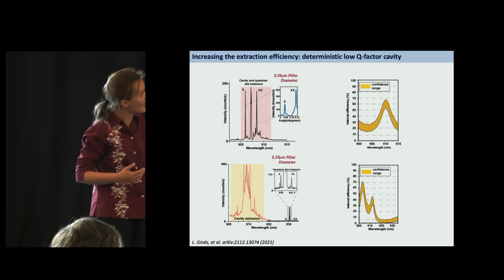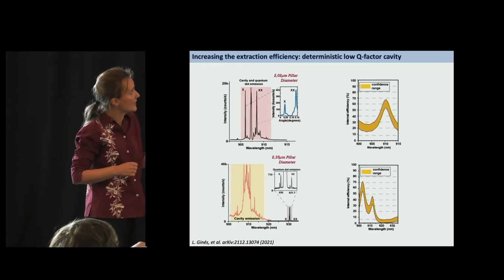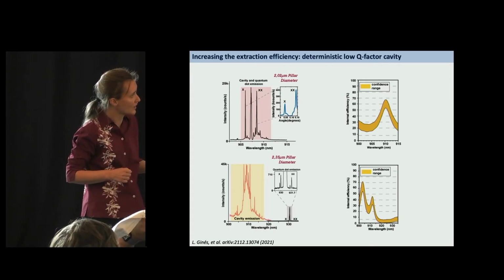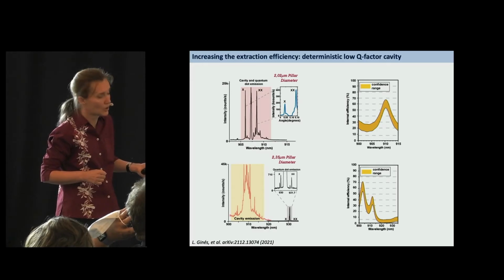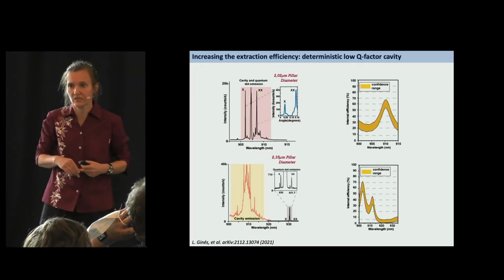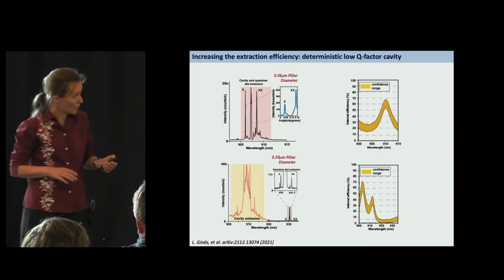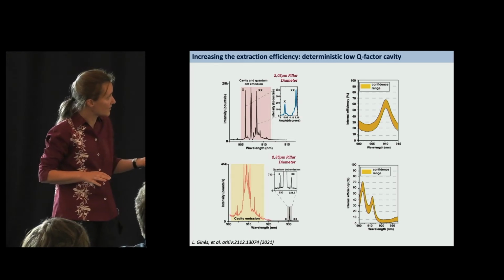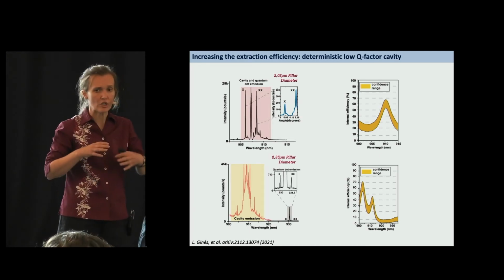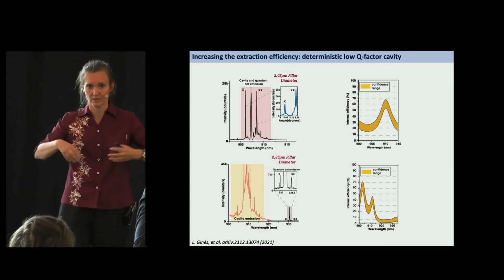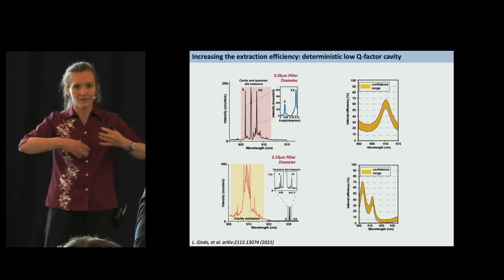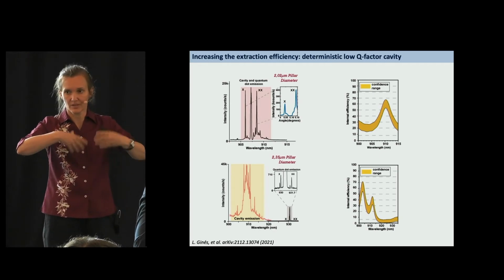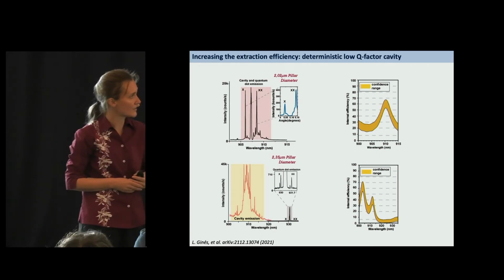So what you can see, very easily, is that the intensity of the emission is much different. Here, we actually need to have an inset because our emission is this teeny-weeny little line on the side. So making this cavity really makes a difference. Also, to make sure that we have a cavity, this is a cavity emission. If you shine a lot of off-resonant light onto this cavity, from all the lights that you excite in the semiconductor material, this cavity will show itself to you where it is.